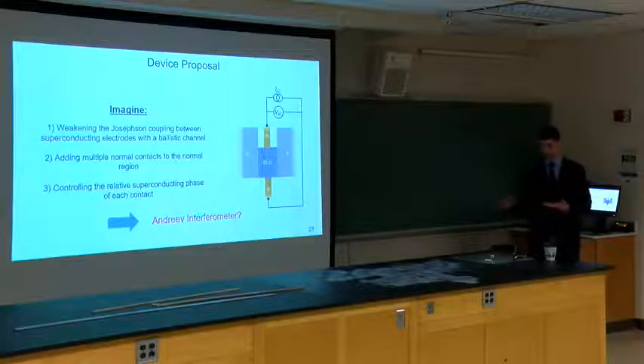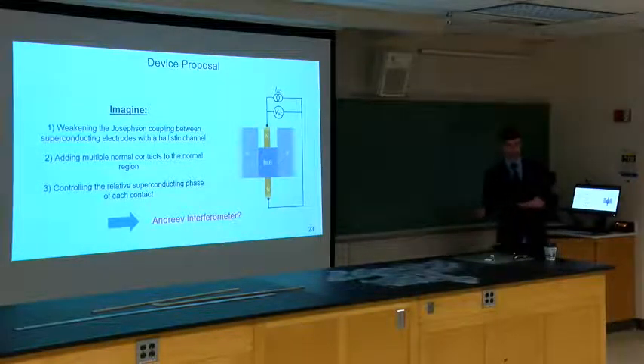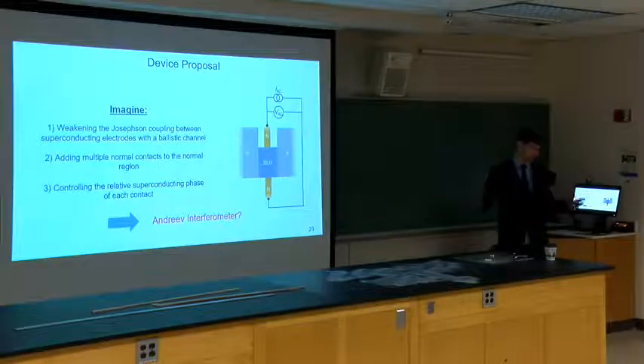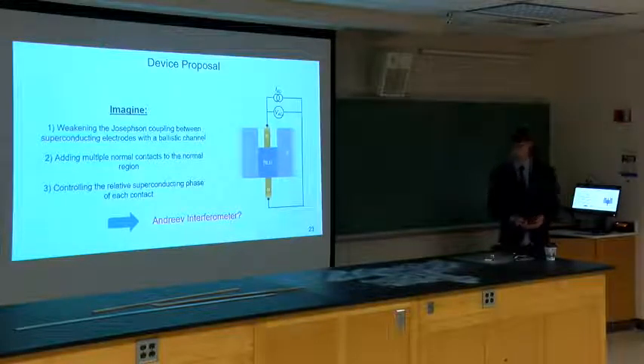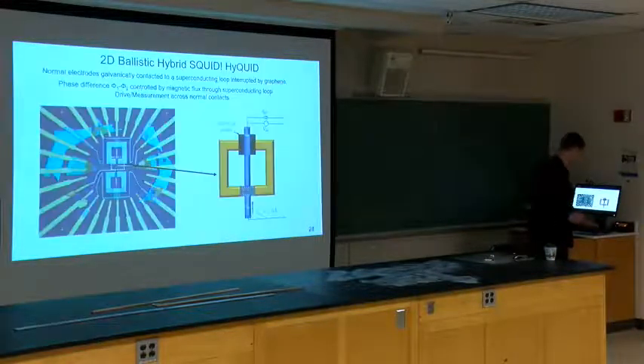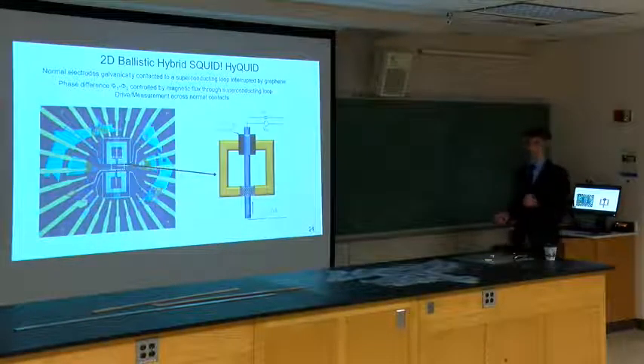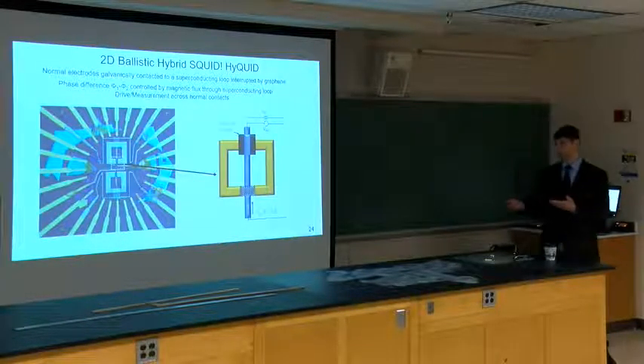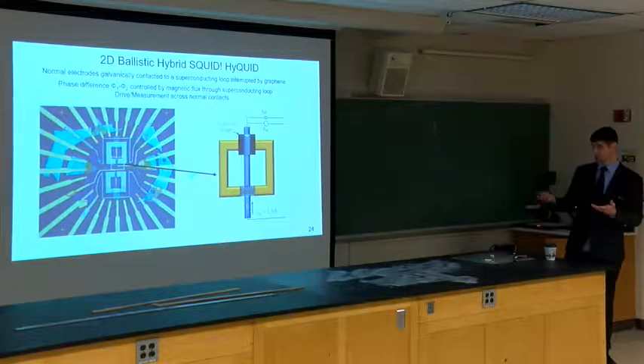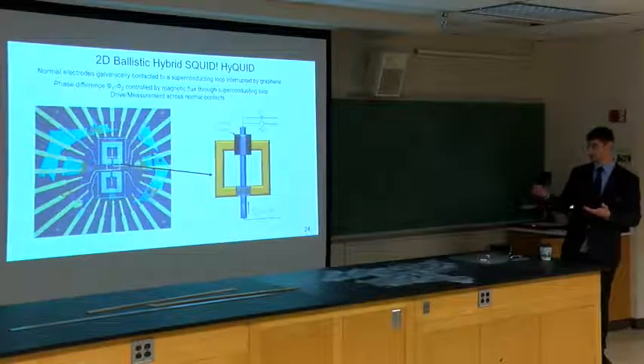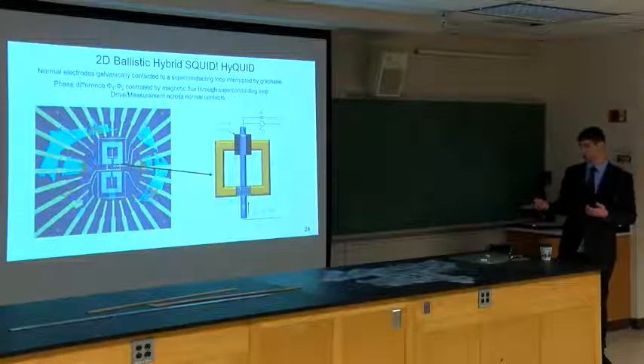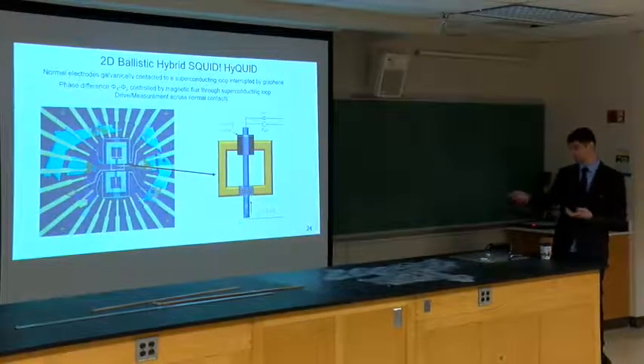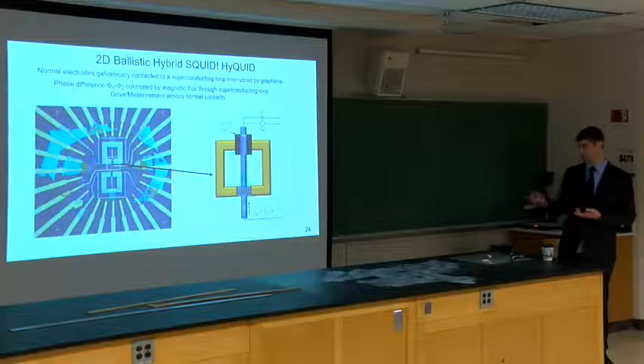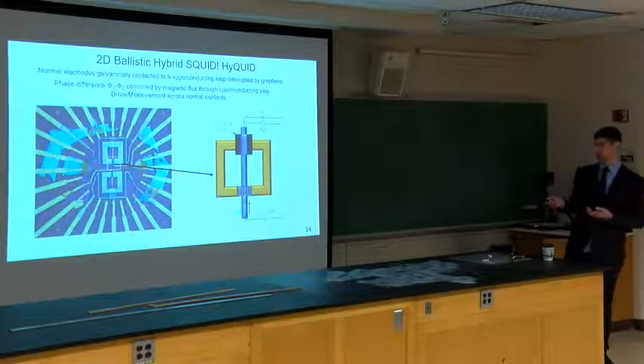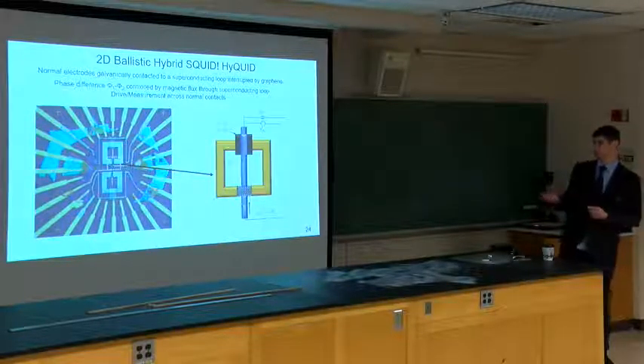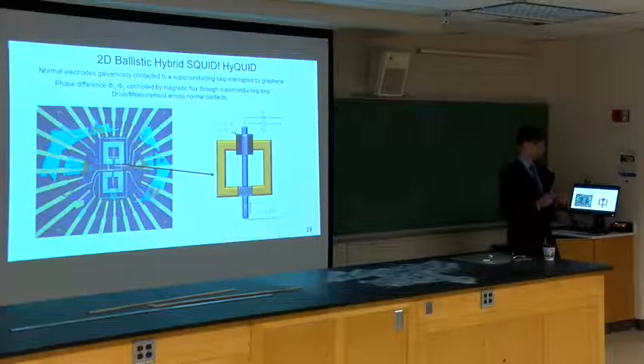Well, it turns out it's similar to a previous device that was kind of hot about 20 years ago, which was an Andreev interferometer. But we have a few more valves to play with because of the graphene. So this is an example device to control the phase. We include a superconducting loop. The superconducting loop is just floating. Well, it would be grounded by the system, and we're only measuring across normal contacts. So we're controlling the phase by magnetic flux flowing through this loop.